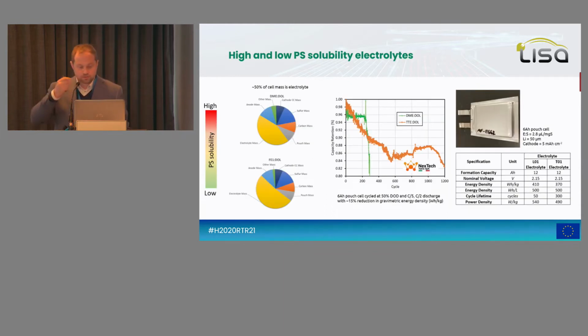This is the first result from Nextech now in the consortium. Here you have more than 1,000 cycles, 82% retention of the initial capacity for lithium sulfur. So here it is limited. This is not 80% depth of discharge, this is 50% depth of discharge. So it means that you no longer have this 400 watt-hour per kilo, but you have to divide by more or less 2. But it's to illustrate what I was showing before.